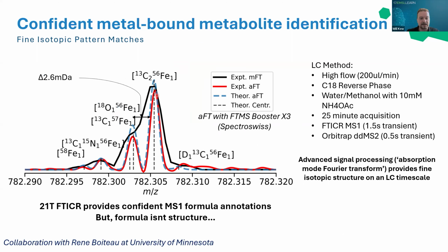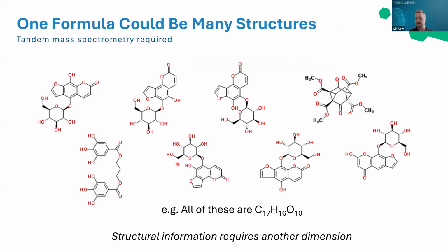In this particular case, we really pushed the instrument hard, and we're able to detect and resolve iron 56, 57, 58, oxygen, deuterium isotopologues, all in this very narrow mass area. This particular type of measurement is essentially only possible at 21 Tesla when you're trying to do things on a chromatographic timescale. Unfortunately, it's important to remember that formula isn't structure.